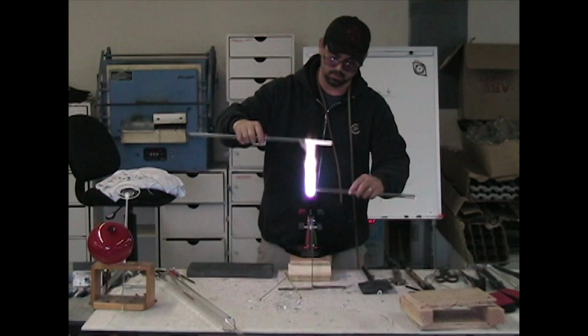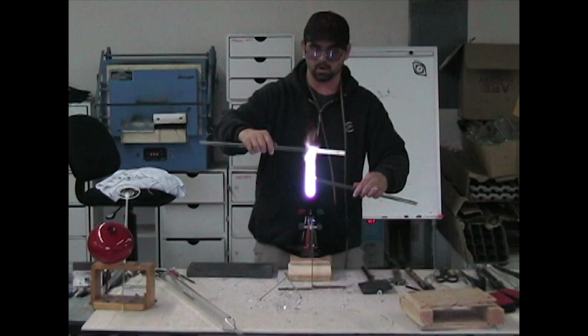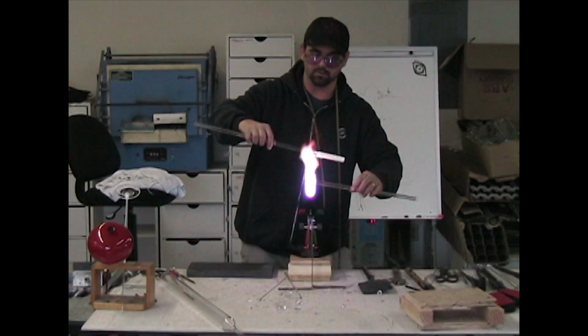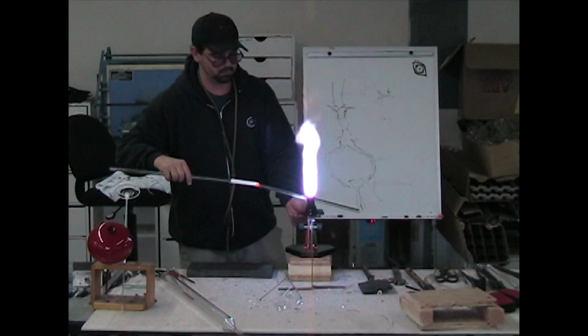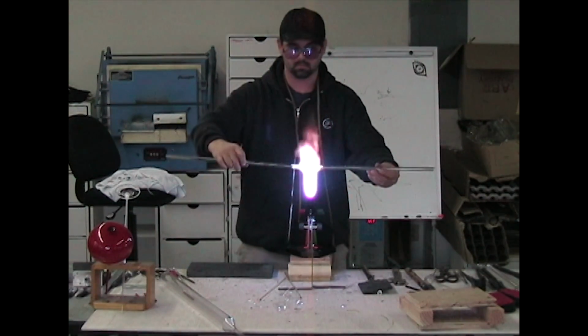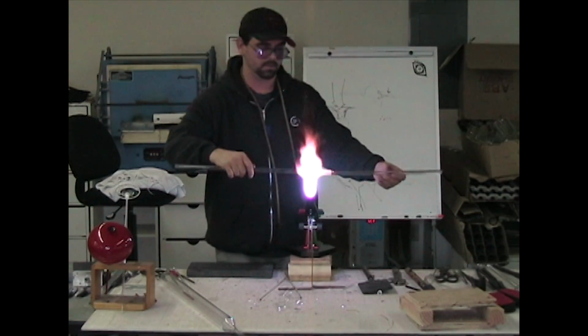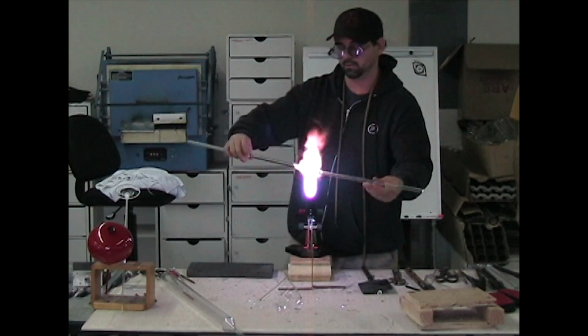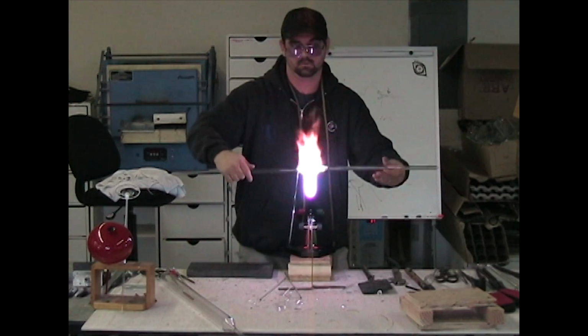Keep it warm back here because I didn't really stick it on there real hard, and the white is actually kind of susceptible to cracking a little bit back from where you seal it with something. So keeping it warm while I'm getting it clear, just as long as I don't get it too hot and where they start wobbling all over, prevents it from cracking. Hot enough, they're all going to move. Feeding it together.